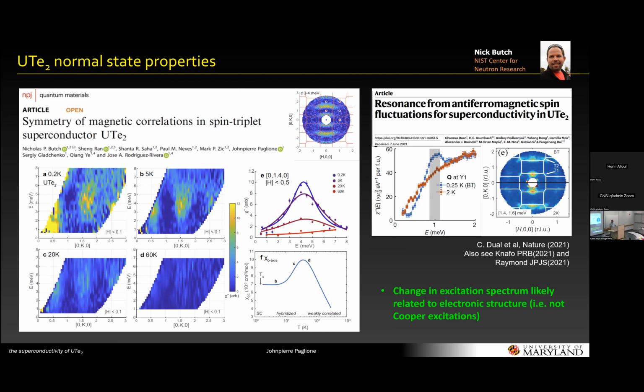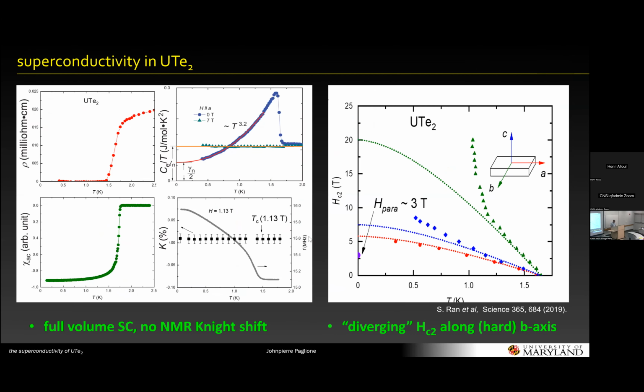Yes, Steve. So in Nick's data, you can just calculate the joint density of states since you know the Fermi surface, right? Does it match basically with what's seen in inelastic neutron scattering? I don't remember if that's been done. Okay. And for instance, in Nick's work, they saw this dispersion continue through the temperature range, and it's not clear. I would say I don't believe that it's a singlet-triplet excitation of the Cooper pairs giving you this resonance. But we can argue about that later.